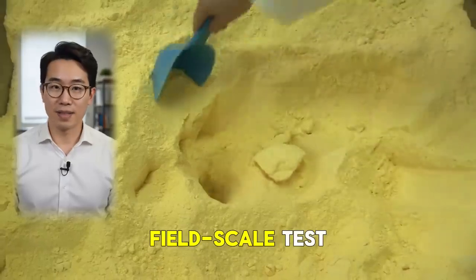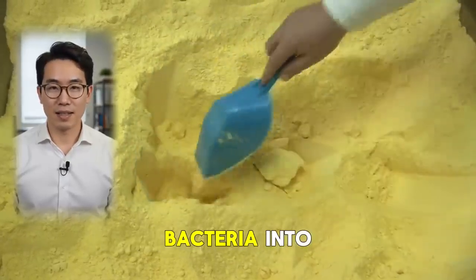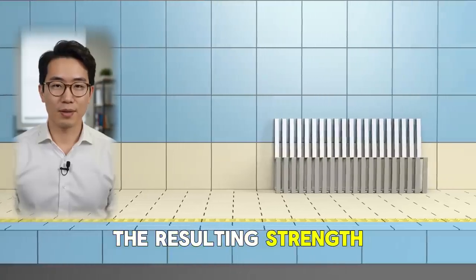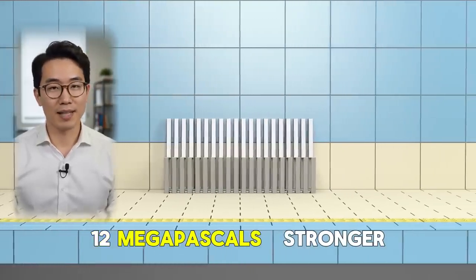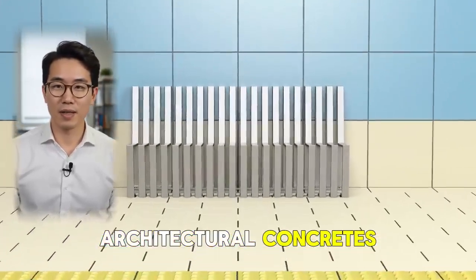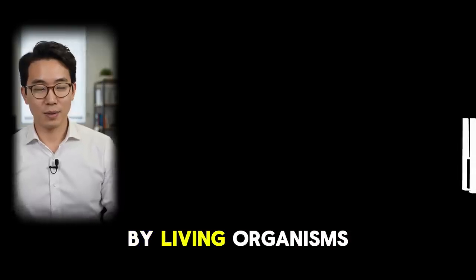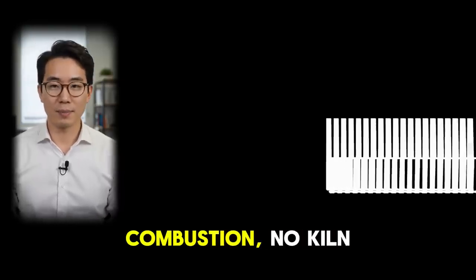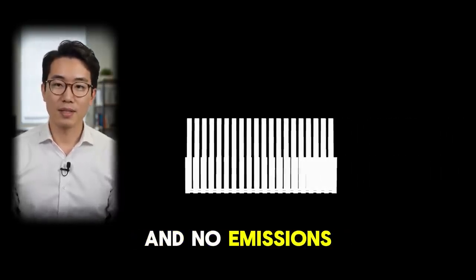In a landmark field-scale test, researchers injected these bacteria into a 100 cubic meter body of fine sand. The resulting strength reached up to 12 megapascals, stronger than some architectural concretes, grown entirely by living organisms at ambient temperature with no combustion, no kiln, and no emissions.